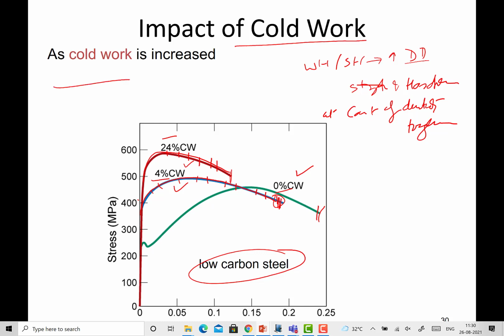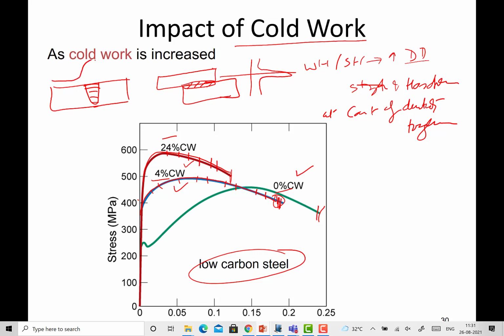So if you take the steel weld joint and develop it using a solid state joining technique, or using ultrasonic welding where micro level deformation is taking place at the interface, in all these cases you will notice that the hardness distribution at the interface goes up like this. Even if there is the same phase, you may see the uptrend in the weld nugget zone or the joint interface area, and this is attributed to the kind of deformation that will be taking place.